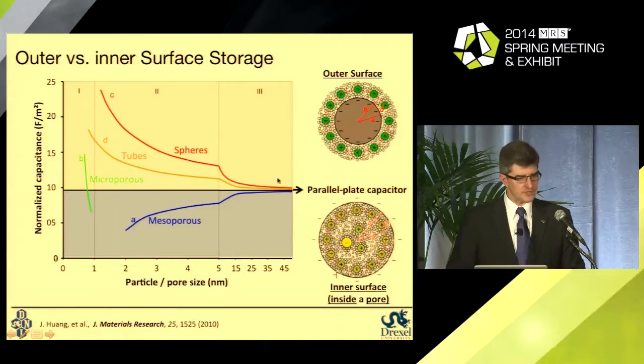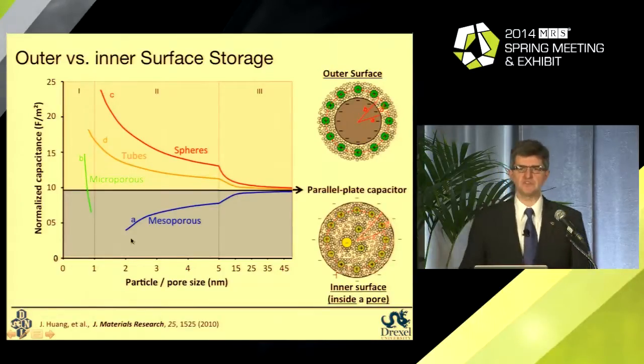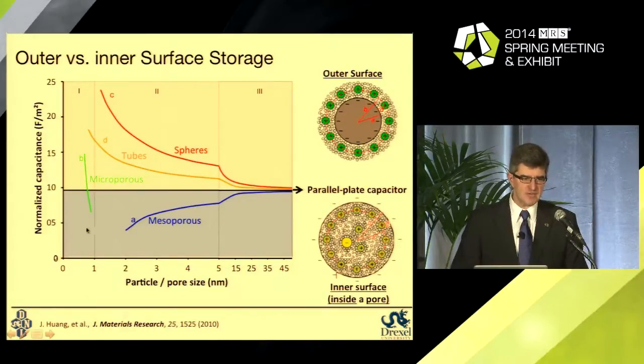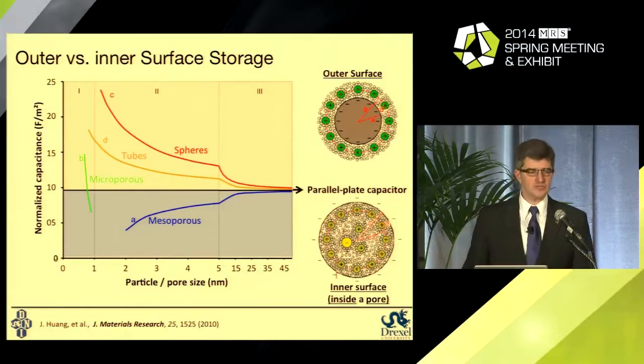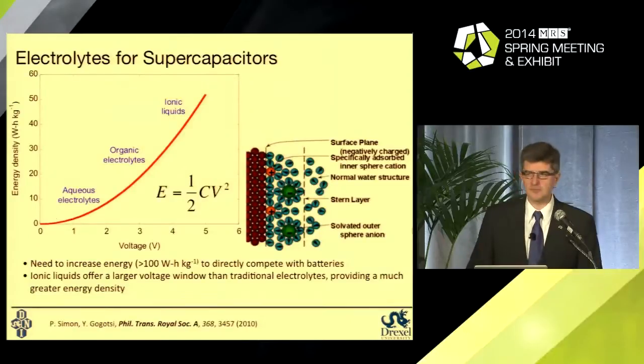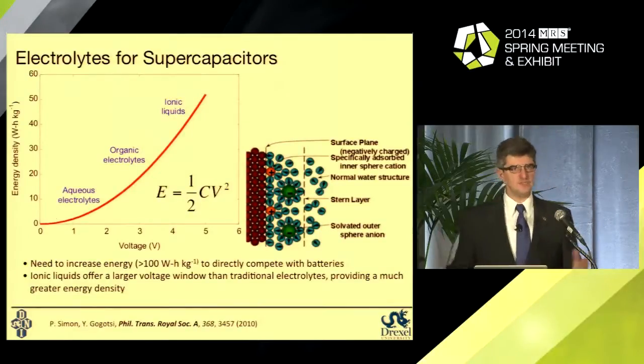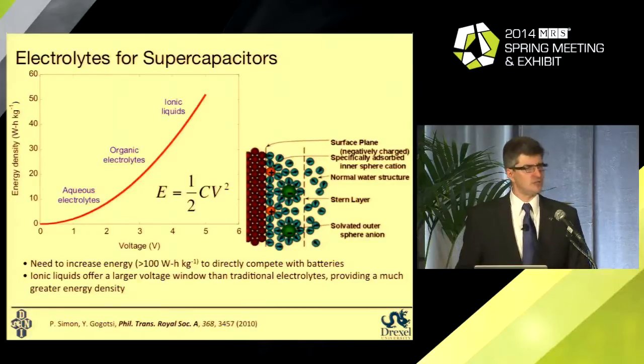Tubes will go here. Planar materials like parallel plate capacitor graphene will be laying in this area. Mesoporous carbon, carbon with pore size larger than 2 nanometer, will show a very different dependence, and microporous carbon will end up here. So again, we need to know how to select the material to achieve the optimum performance here. Moreover, if you design an electrical energy storage device, a supercapacitor, you have carbon electrode and you have electrolyte.